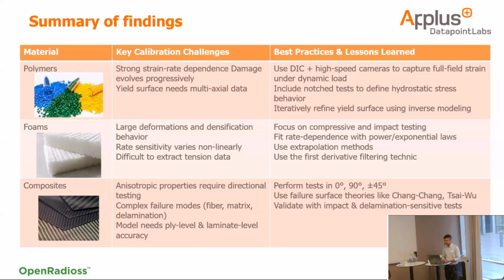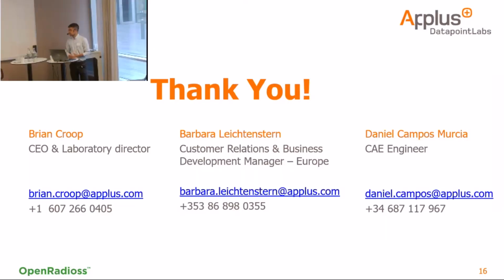For foams, the main difficulty or challenge is the large deformation and the densification behavior. Here, the important part is the filtering of the derivative, as well as trying to extrapolate the data as smoothly as possible, so you can have good smooth curves. And finally, for composites, strain rate dependency is not that high, at least in the ones that we have tested. It's important to define which modeling strategy you want, whether you go by ply, or a more laminate model, or any homogenization or whatever. But again, if you have a composite, test it at different orientations, under as many different conditions as possible. So that was all for me.